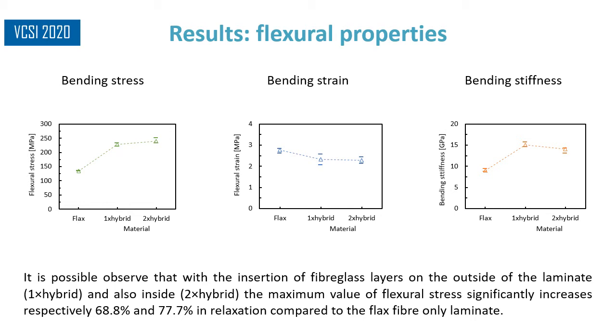In terms of bending stiffness, there was an increase when the outer layers of fiberglass were added, 1x hybrid, but a decrease compared to the previous one when the intermediate layers are introduced, 2x hybrid. Finally, with regard to flexural strain, the values decrease for 1x and 2x hybrid.